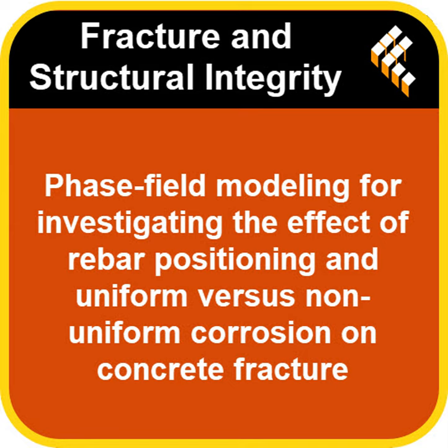Configuration 4D10T3. Oh, now this is where the difference between uniform and non-uniform corrosion really stood out again. Big differences. Okay, tell me. Uniform first. With uniform corrosion and these edge-placed rebars, they saw cracks going out to the nearest edges, but also this distinct sort of diamond-shaped crack pattern forming between the rebars in the center of the section. A diamond shape? Huh. Okay, and non-uniform.